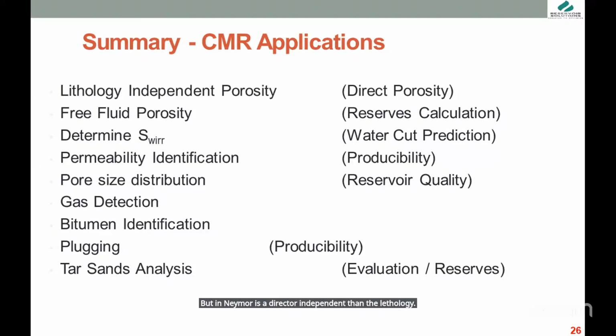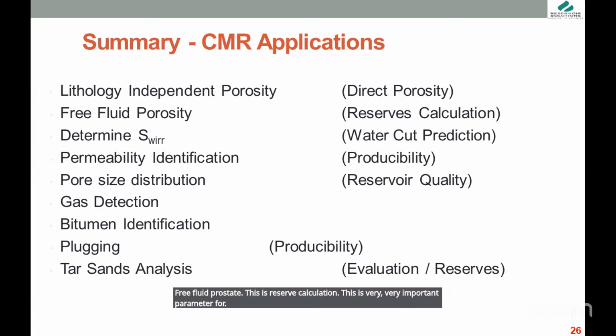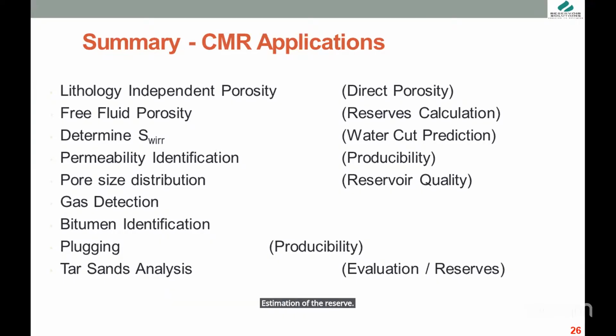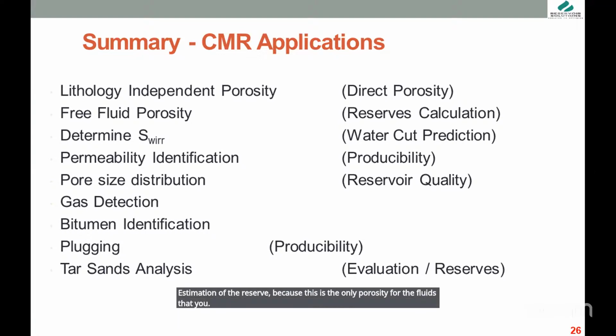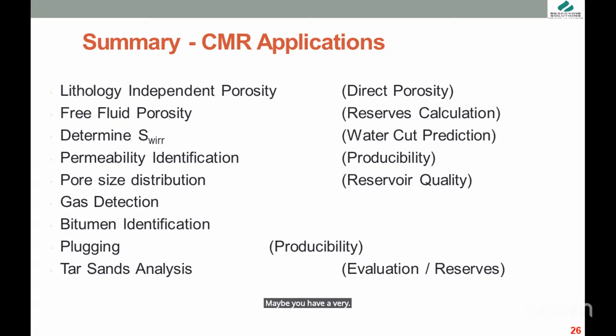Free fluid porosity, this is reserve calculation. This is a very, very important parameter for your estimation of the reserve because this is the only porosity for the fluid that you can produce from your reservoir. Maybe you have a very high total porosity, which exceeds 25 to 30, but the free fluid porosity is just only 8 to 10%.